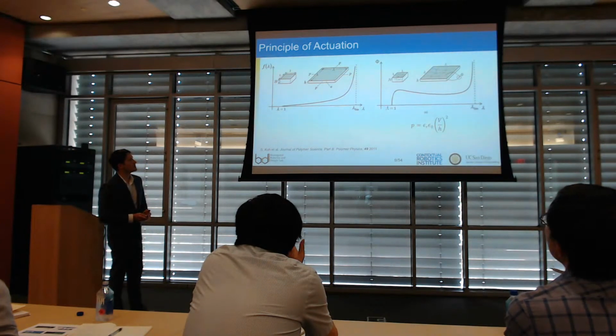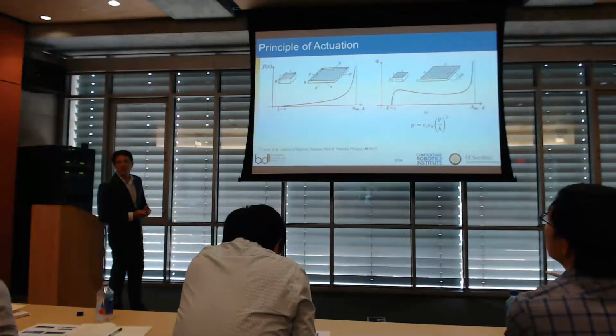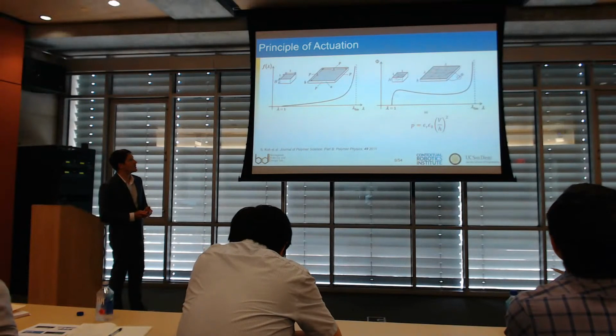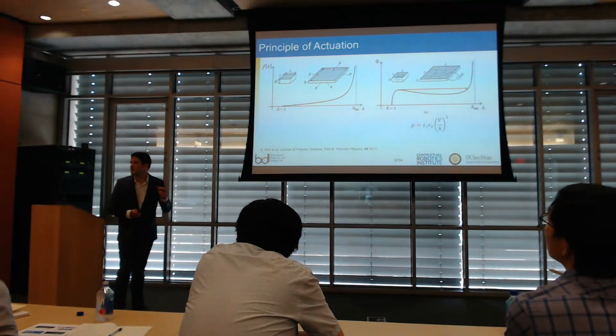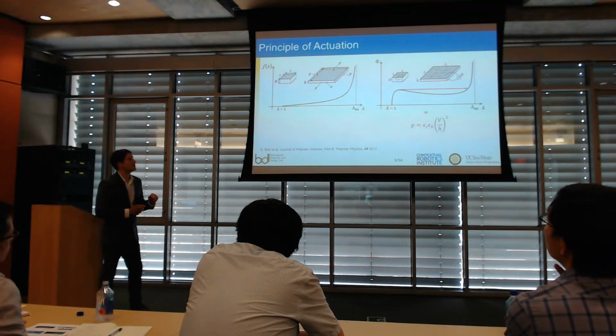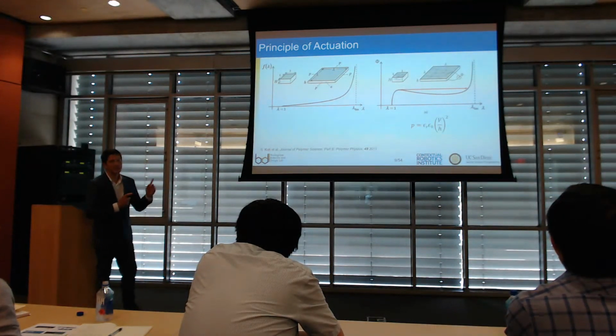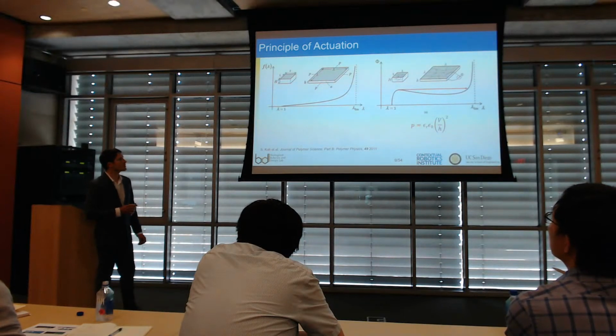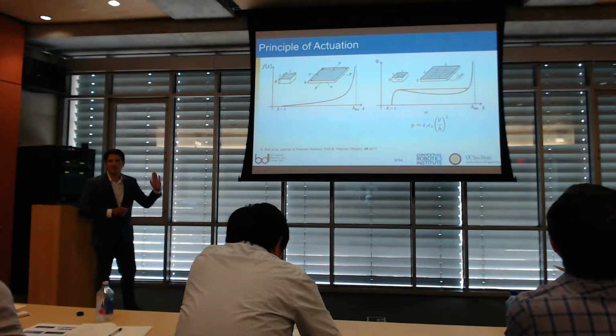Okay. So as you increase the voltage, you get a small amount of strain, and then right around here, this is maybe around 30% or so. What's going to happen is that as you keep the voltage constant, it's going to become bistable. So you could jump from this position all the way across to the following position at the same voltage. And so what that means is that if you can get to that point, you can actually get very large deformations with these materials. The trouble with that is that different materials have different breakdown strengths.